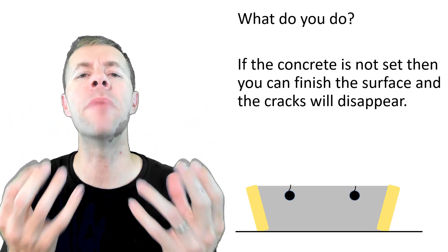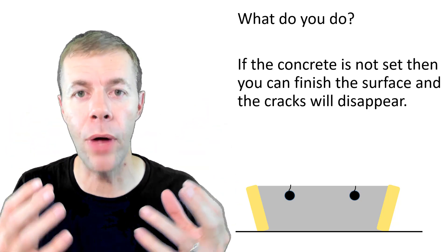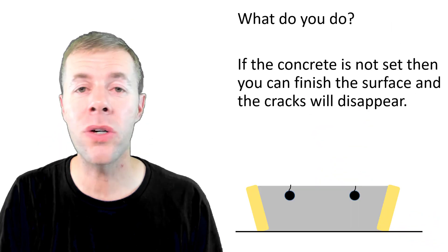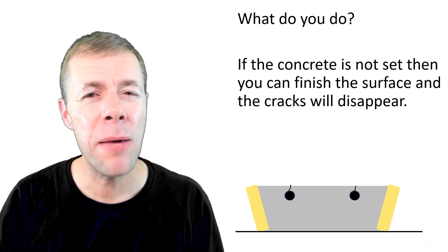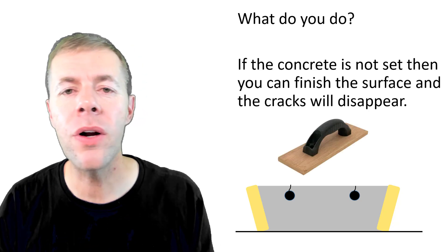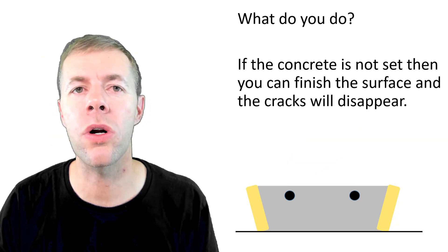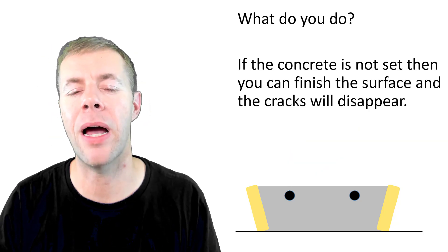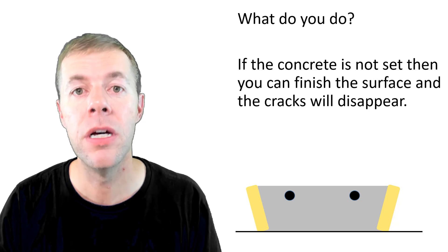So what do you do? What if you're on the job and you see this has happened? You're like, crack, I see a crack. If the concrete's not set, then baby, you get back out there and you refinish the surface. You get your float back out there and you work it and work it and work it and you try to close those cracks back up. You can make them disappear on the surface.